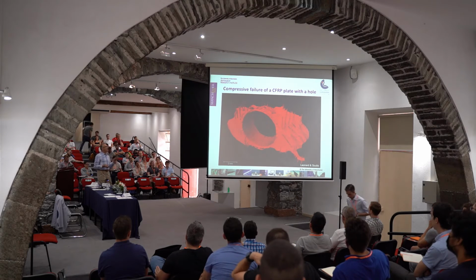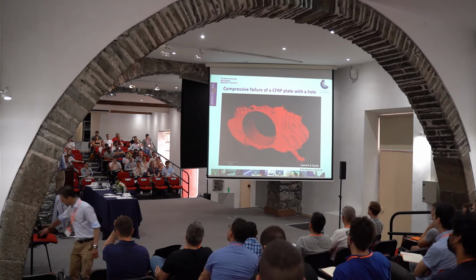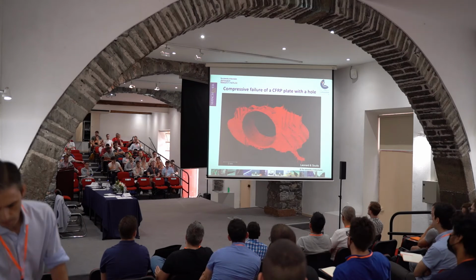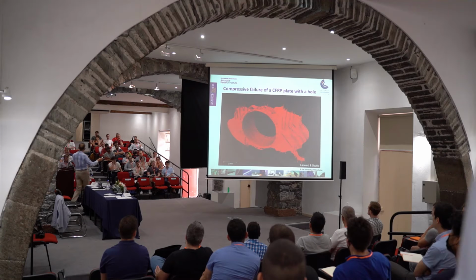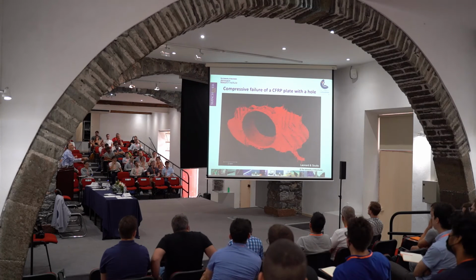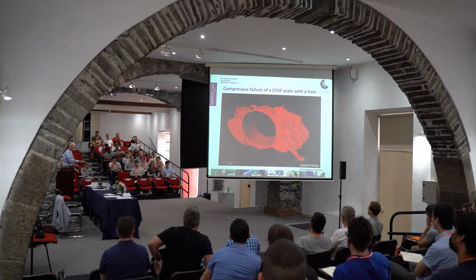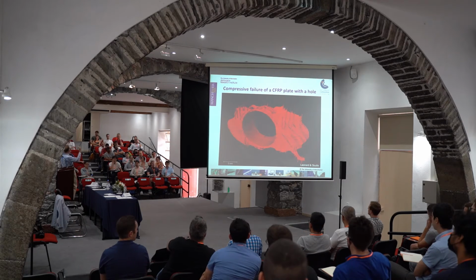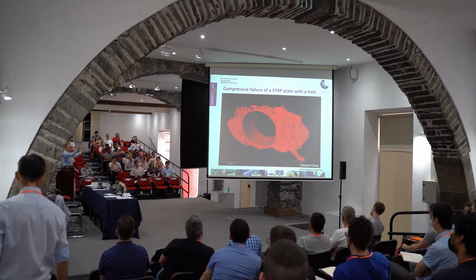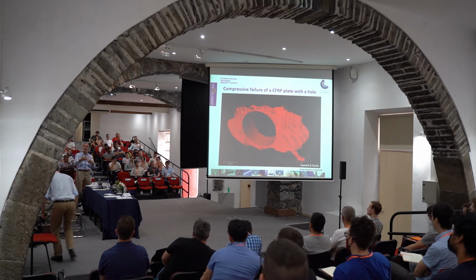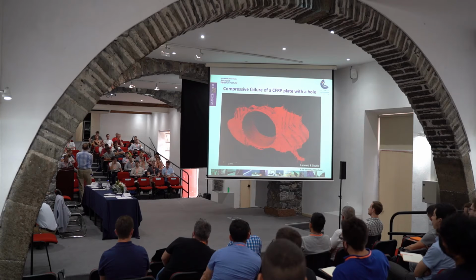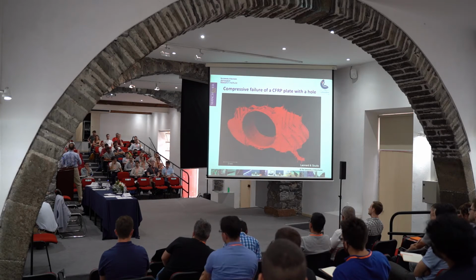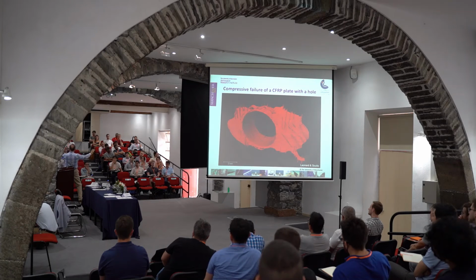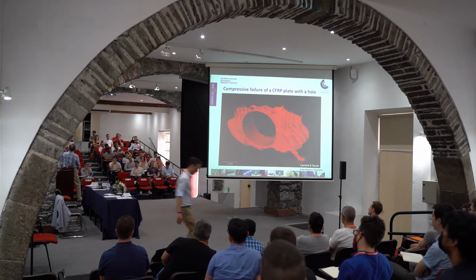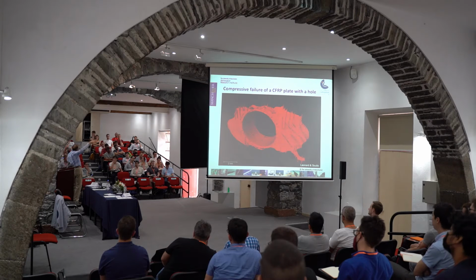And then when you try to visualize the damage using X-ray computed tomography, what do you see there? Who's going to describe it? You see actual cracks in the zero ply, off-axis cracking, because we've said that these develop delamination. So those cracks are surrounded by delaminations. They cause local delamination, separation of the plies. Which of course, when you're in compression, means that now your zero layer that supports the actual stress has lost its lateral support and will microbuckle earlier. So that local delamination reduces the support of the zero plies that carry the actual stresses, and will reduce the strength of my multidirectional laminate.